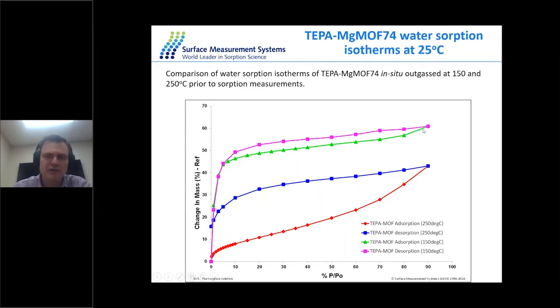So MOF outgassed at 150 gives you almost twice as high adsorption capacity, with very small hysteresis, compared to the same MOF outgassed at 250 degrees. Also, in this case, basically we observe a thermal degradation of the MOF because the temperature was too high for this material. So just to see, because the reason I look into this,